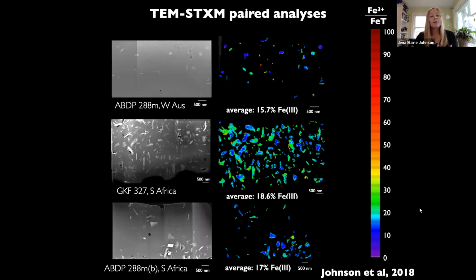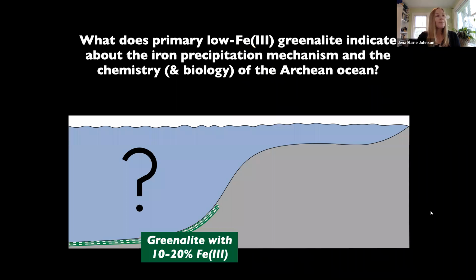And 3 other well-preserved chert samples with nanoparticles had extremely similar distributions, with these well-encased particles having an iron 3+ content of around 10 to 20%, while particles that appear more recrystallized or associated with cavities have a higher iron 3+ content. Okay, so the most primary particles are greenalite, with 10 to 20% iron 3+, but dominated by iron 2+.